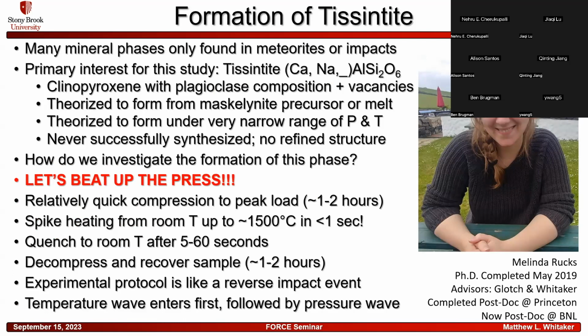And it was theorized to form from a maskelynite precursor or a melt and a very narrow range of pressure and temperature. But it was, at the time, never successfully synthesized, and there was no refined structure for it. So how do we investigate the formation of the phase? Well, we proved previously that we can beat the press up by going to very high load very quickly. So what happens if we do the same thing but with temperature this time?